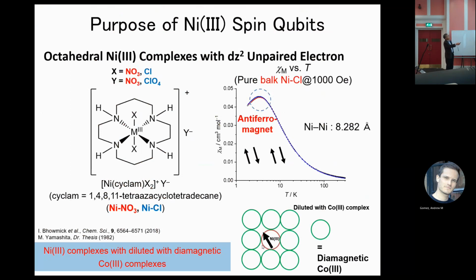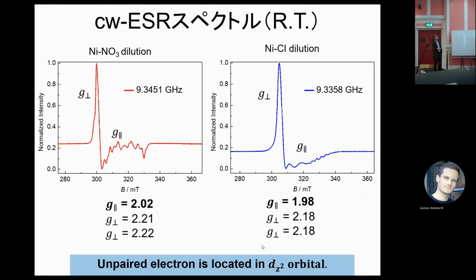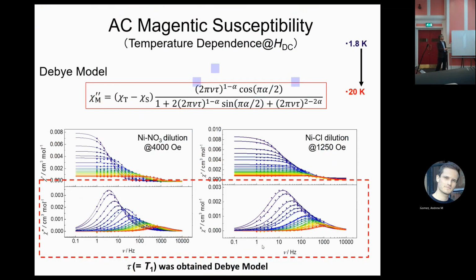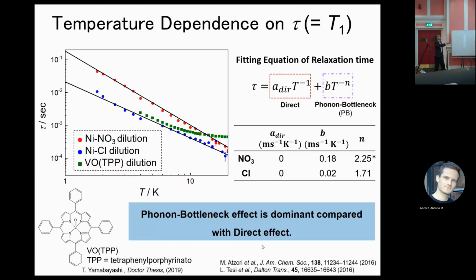You can see bulk NiC chloride shows antiferromagnetism due to the Ni(III) antiferromagnetic interaction. However, diluted in diamagnetic cobalt, we isolated one Ni(III) atom. So both Ni(III) compounds show the unpaired electron located in the dz2 orbital because of the halide. So both compounds show the slow magnetic relaxation. This is not a single-molecule magnet, but a phonon bottleneck effect. So this is the result. Red one is Ni-NO3. Blue one is NiC chloride.